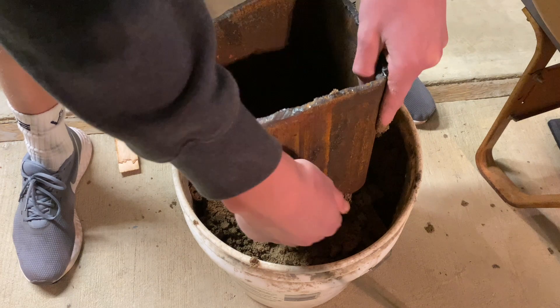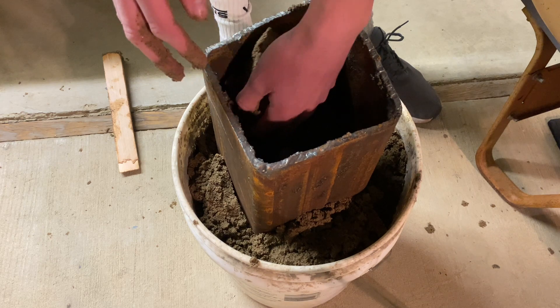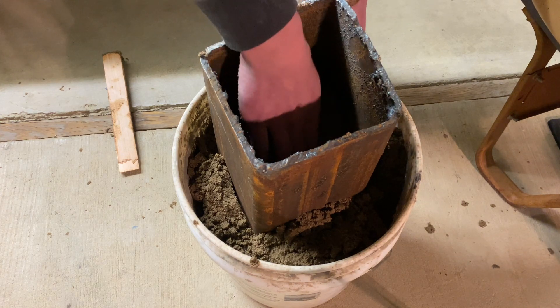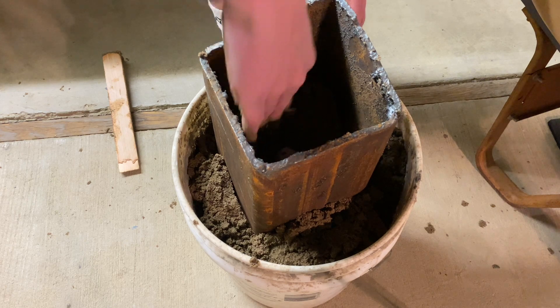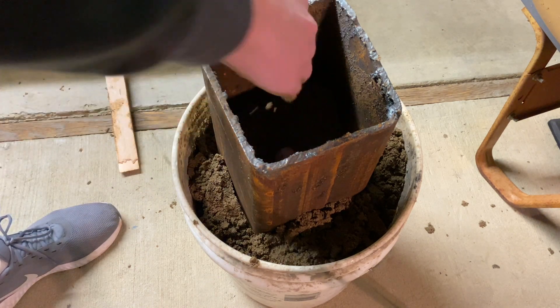Here you can see I added a large square piece of steel, and I'm doing this instead of the flower pot because I realized the hole at the bottom of the flower pot was too restrictive for all the molten metal — it just wasn't allowing enough of the copper to flow through, and I think that's why I had a failure last time. So hopefully this new idea should work. What I'm going to do with the sand is slope it all inward, leading directly to the bottom, which will be the foam part in the center — you can see right there, I'm using a flashlight to point.